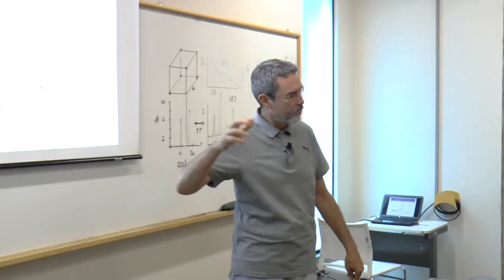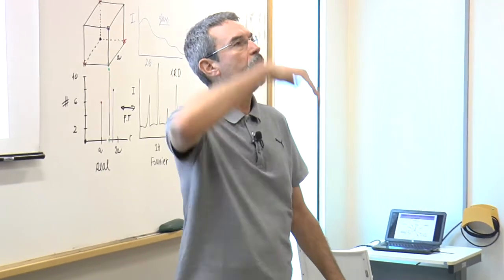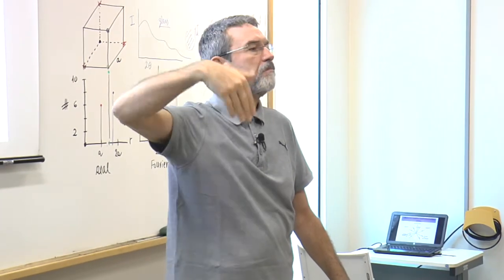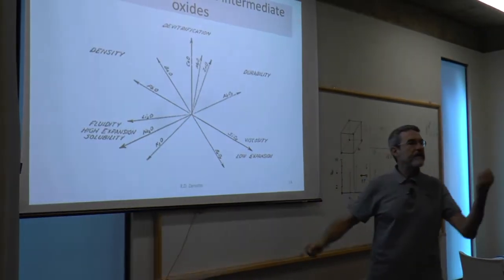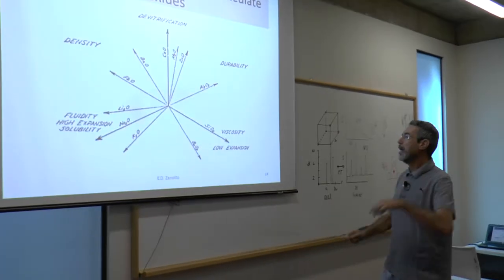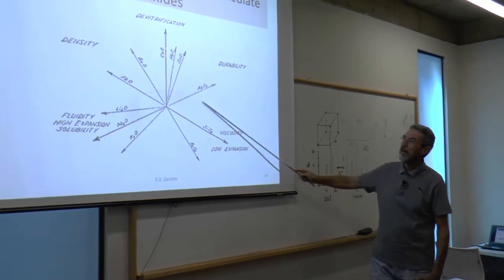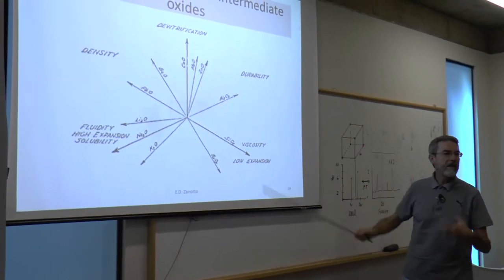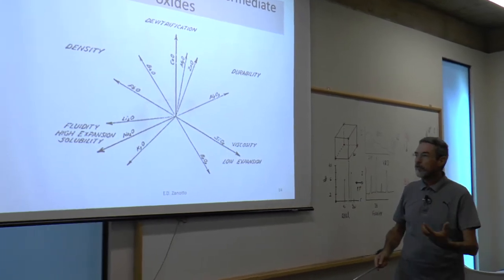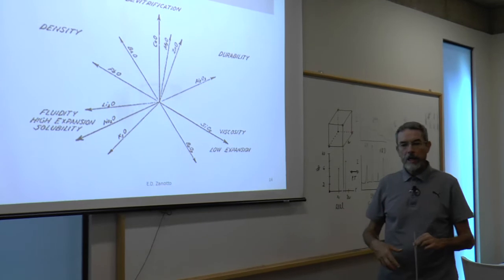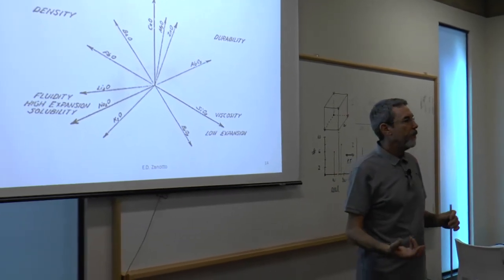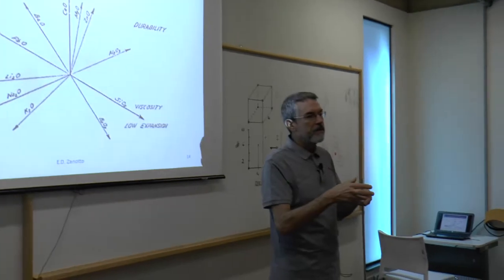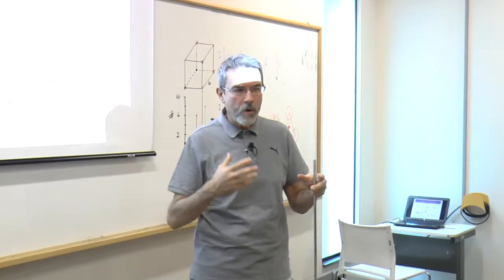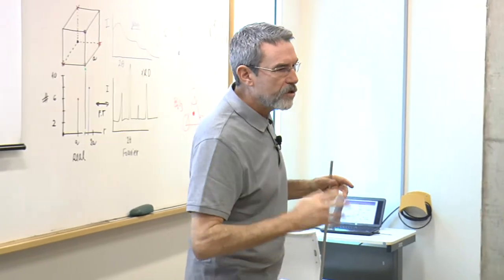We add to silica glass, drop down the temperature from 1850 down to 1300 or so. But however, they also decrease the chemical durability of the glass. So we add, for instance, alumina or zirconia to increase the chemical durability. What I'm trying to say is that in real life, we add certain elements, and not by chance. People already know more or less the effect of each element to a certain glass.